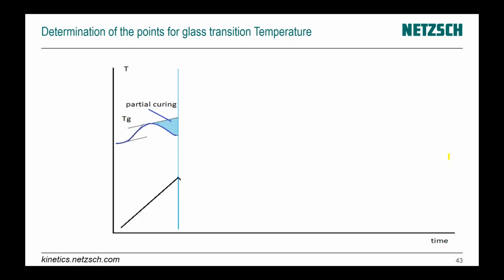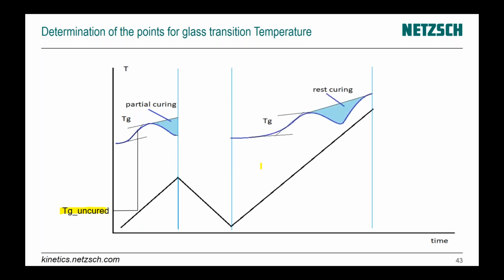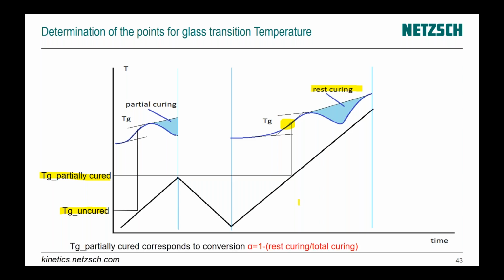Firstly, we make heating with partial curing, not until the end. Glass transition temperature is the temperature for the uncured material, then we make cooling and heating again. The next glass transition here is higher than the first one because the material is partially cured and the glass transition temperature has moved. From rest curing, we can find a value of alpha which corresponds to this partially cured glass transition.